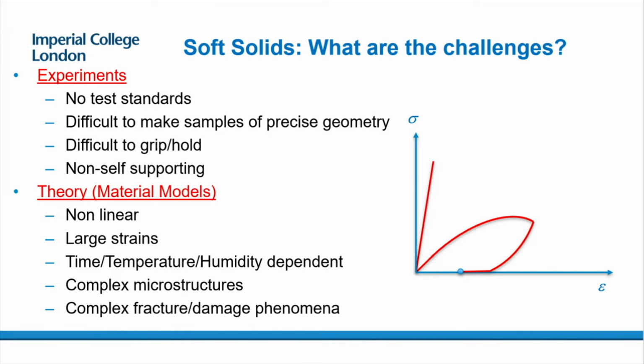These permanent deformations are usually a result of very complex microstructures. A lot of these soft solids are natural polymers with complex microstructures, and that makes this behavior quite tricky to model. The other problem is that this material, when you're testing it, if you slightly change the temperature or the humidity or the speed that you're doing the test, you're not going to get very large differences, whereas this material here will show a huge effect. So these are all the things that make modeling these materials very hard.